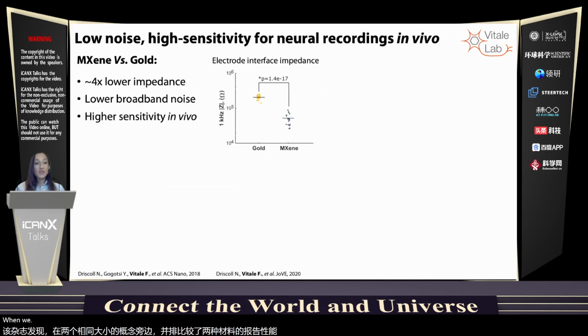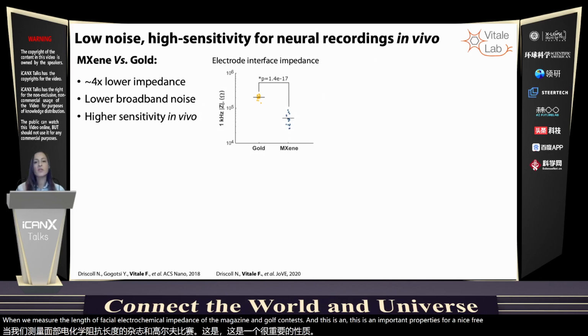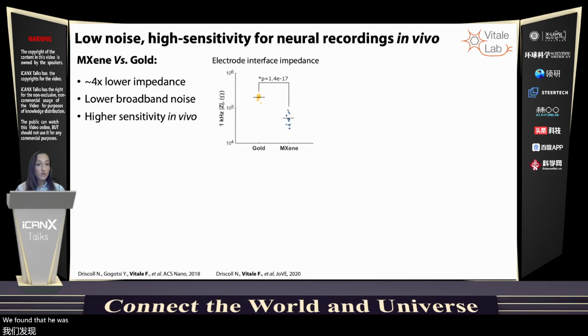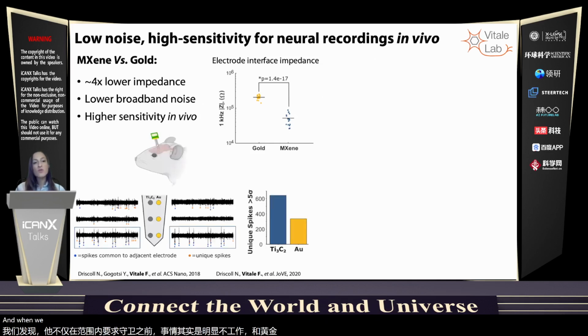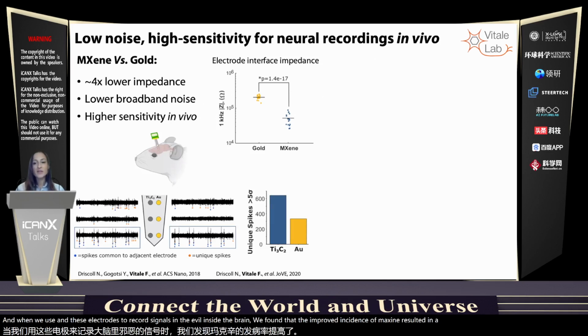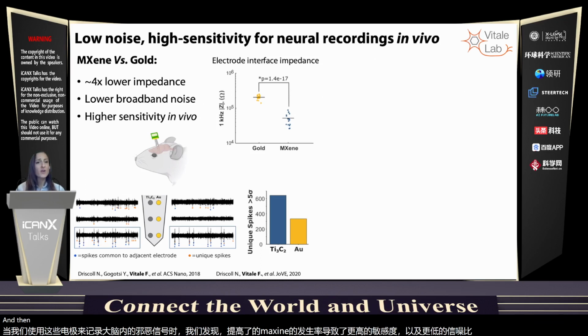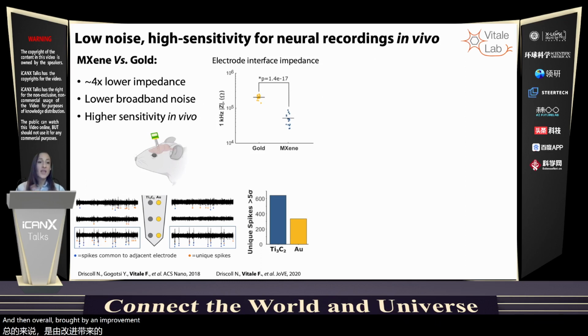When we measured the interfacial electrochemical impedance of the MXene and gold contacts, and this is an important property for noise-free recordings, we found that it was not only in the range required for neural recordings, but actually was significantly lower than gold. And when we then used these electrodes to record signals in vivo inside the brain, we found that the improved impedance of MXene resulted in a much higher sensitivity and higher signal-to-noise ratio, and an overall broadband improvement in the quality of the recordings with MXene.